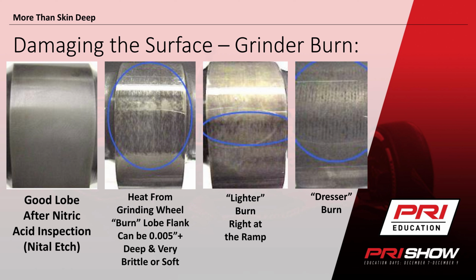And you can see after they run the nital etch, you get that lobe that looks like this nice gray over there. If you have made it either harder through making it really hot and quenching it, or softer by getting it hot and tempering it, it will change the color. So you look at this next one, you put nital etch on it, and it will go in there and turn black.